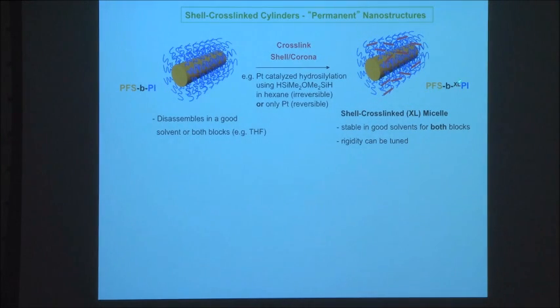So we write this as PFS block XL for cross-linked polyisoprene. And so this should now be stable in good solvents for both blocks. It should be blocked towards dispersion. And I'll show this in a moment. So you can do this irreversibly using platinum-catalyzed hydrosilylation. But you can also just add platinum zero complexes, which will bind the olefinic groups. And then you make cross-links which are reversible. You can remove them again by adding a phosphine. So you can go back. So you can actually do both irreversible cross-linking and reversible cross-linking. In this lecture, we'll mainly use irreversible cross-linking.